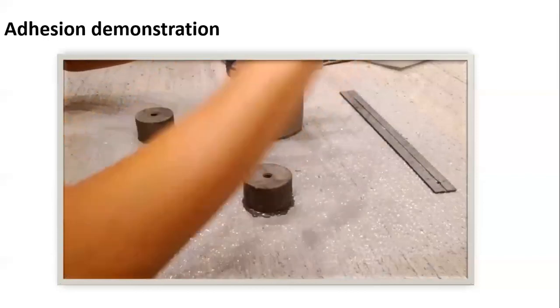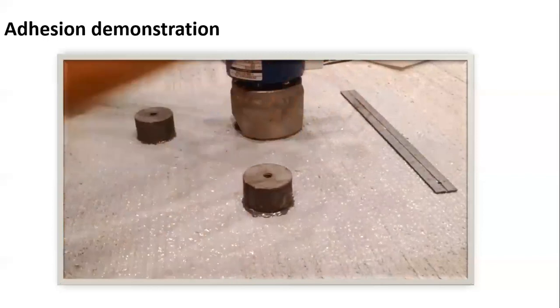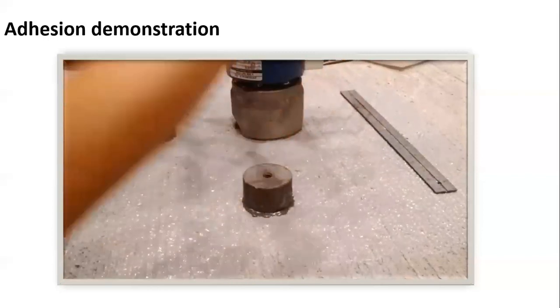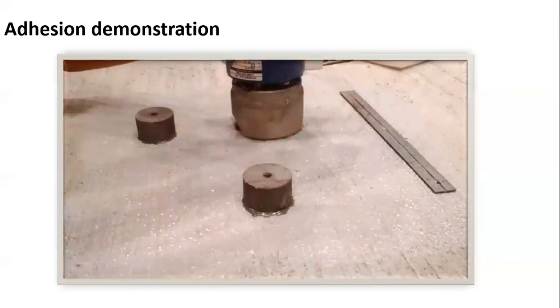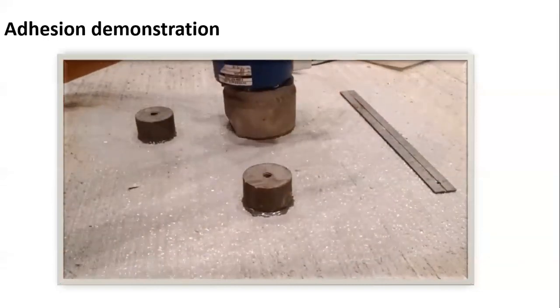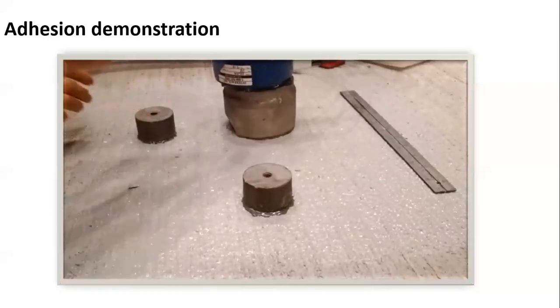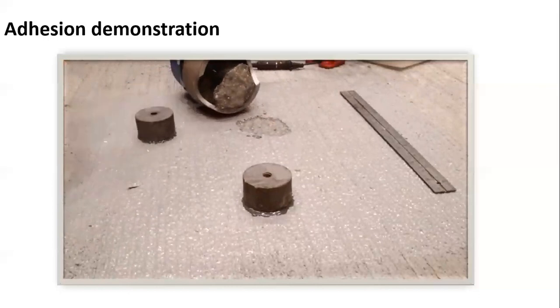For a similar demonstration on concrete, we apply a 4 mil single coat of Tank Coat 160. It was cured for 36 hours on a well-cured concrete slab, approximately 9,000 psi, about 3 times the strength of common floor slabs. 4 2-inch diameter steel discs were bonded with epoxy and pulled to failure. In every instance, the concrete failed rather than the tank coat failing.